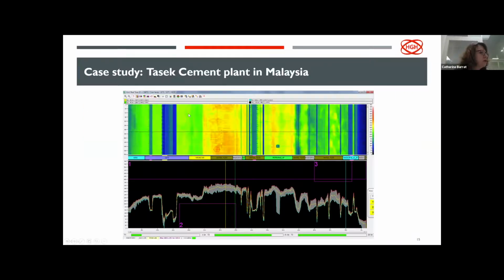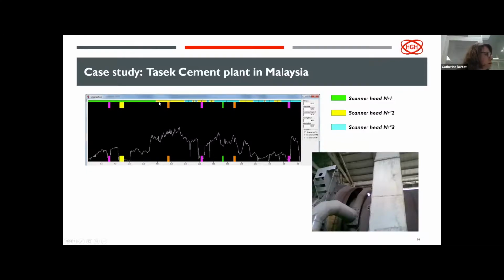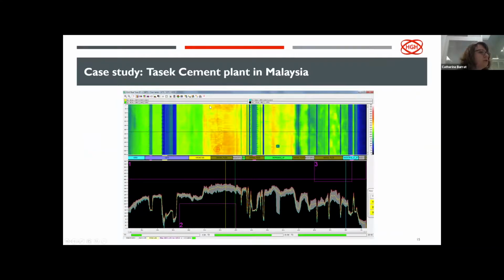And thus we obtain the recombined thermal image for this kiln shell. And maybe you did not pay attention, but the junction between scanner number 1 and scanner number 2, somewhere here, is actually located on the thermal image here, and we can't see any difference. The signals and the measurements are synchronized, harmonized, and rephased to provide a single seamless thermal image of the shell.